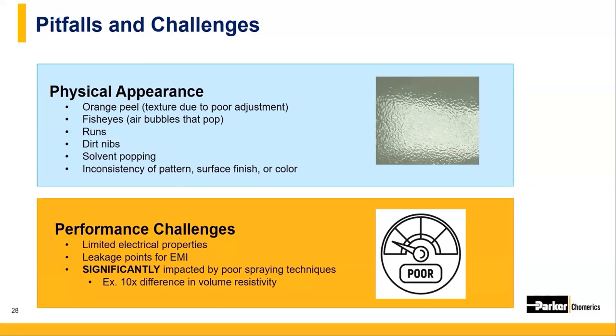And we had a customer call and tell us that after painting their substrate, it had actually failed EMI testing. We were able to take a look at the photos that they sent and could deduce the problem right away. They had a very experienced paint operator who unfortunately had never actually worked with conductive coatings before and was unaware of the mixing requirements. When they sprayed the paint, the heavy particles sunk to the bottom, and some of the particles actually got sprayed out in clumps across the surface area. Coatings typically have flake-shaped particles and are meant to lay flat, thus coating the entire surface to block and shield EMI.